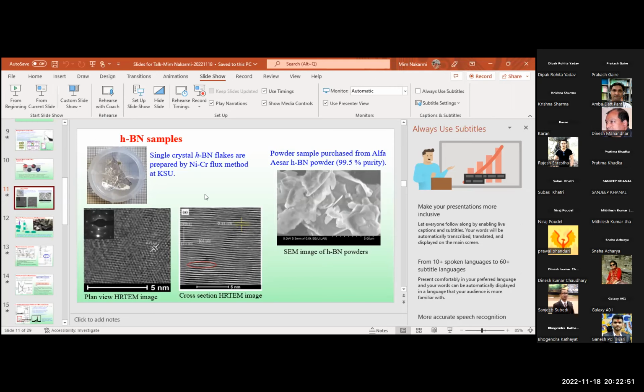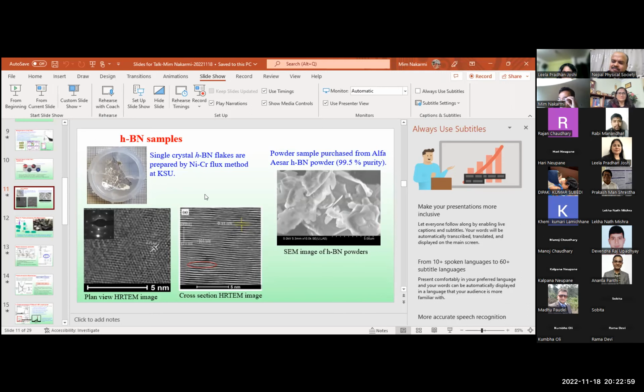So something like sputtering? No, it's not sputtering. It's a single crystal growth. We melt the material, heat it to a very high temperature, maybe 2000 or higher than that, and then slowly cool it down. It crystallizes. It's not thin film technology. It's a powder sample, you said, right? No, it's a single crystal technique. Okay.